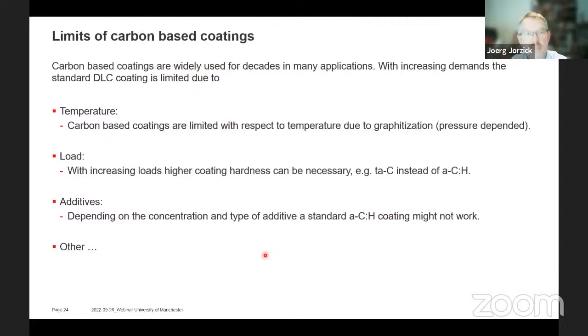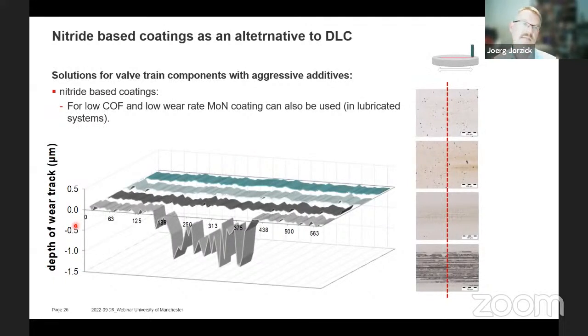Limits of carbon-based coatings. I already talked about temperature, and here we always have this graphitization, especially as soon as we have the carbon-based coating, the DLC structure and the sp3 bonding is converted to graphite bonding. We can also have examples where the load is getting too high. Here we can shift the border a little bit by applying a harder carbon-based coating, so using a TAC, a hydrogen-free very hard coating compared to the PVD coating or additives. And please allow me to go a little bit deeper into the additives, because here we did a test. This test was quite simple.